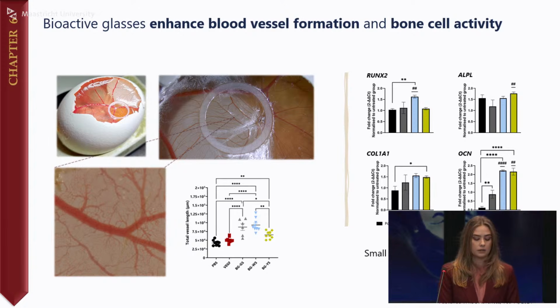They were not identical. For example, we observed that overall, bioactive glass synthesized from gray sand and white sand had the strongest effect on the vasculature, while the bioactive glasses synthesized from white sand and yellow sand had slightly stronger effect on the gene expression related to bone formation. Furthermore, this chapter showed us that bioactive glasses derived from natural resources have a potential for a successful and sustainable bone regeneration.